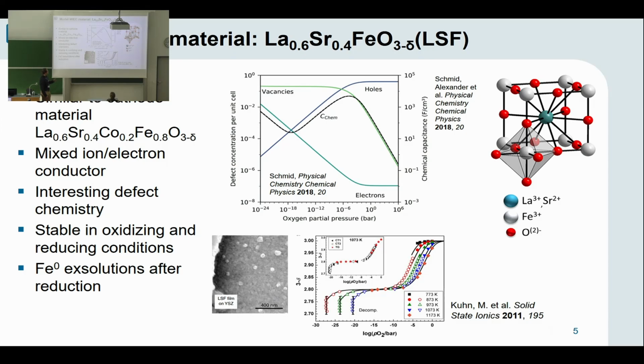And it's shown here in the so-called Brouwer diagram, where the point defect concentrations are plotted versus oxygen partial pressure in a double logarithmic scale. And what you can see is that LSF is a p-type hole conductor in oxidizing conditions, with a comparatively small amount of oxygen vacancies in oxidizing conditions.